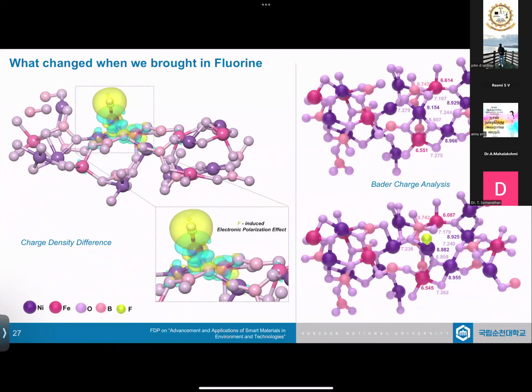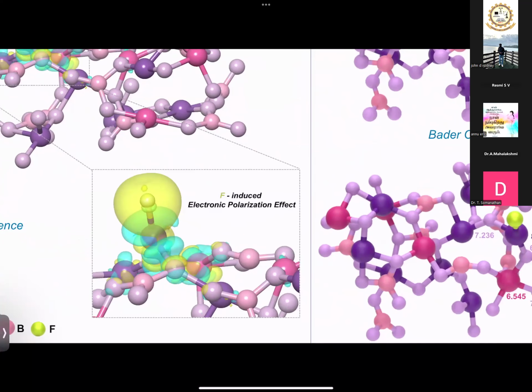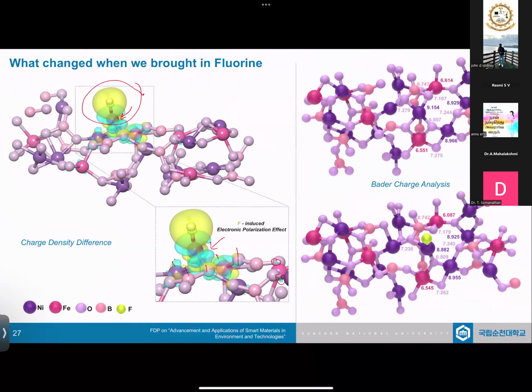So what did we do? We still wanted to understand why fluorine is doing it. I needed to prove that the nickel atom is being altered, which is being proved. We did a charge density difference study, and we found out that because of its electronegativity, you can see over here, the nickel atom is extensively being altered. The energy is being altered, and also the surrounding nickel atoms and boron and oxygen atoms are all being altered. Also the iron atoms. This is something that we saw in our XPS and other studies, that iron is also being affected. This is called a remote ligand perturbation, where remotely the iron atoms are being altered.